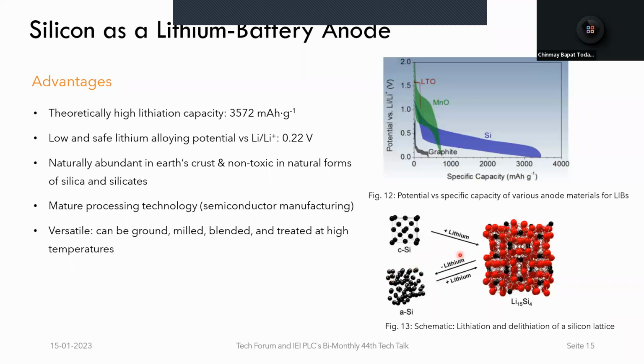Upon lithium insertion, the lithium and silicon alloy together, and we have a lithium silicon alloy as the intermediate stage. During lithium extraction, the crystal structure gets disintegrated and we have the formation of amorphous silicon. This alloying reaction is different from the graphite intercalation that we saw before, and this is the reason why the specific capacity of silicon is that much higher than graphite.